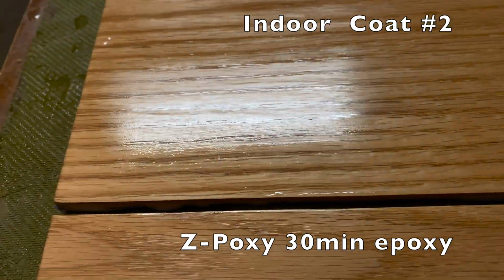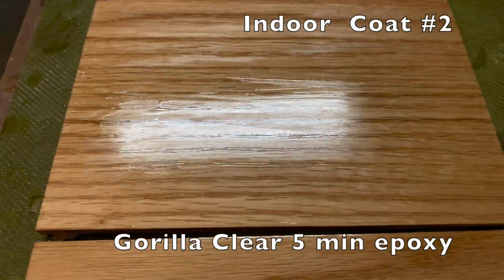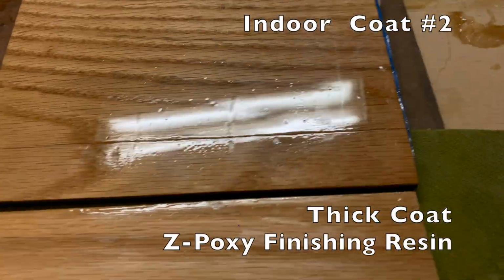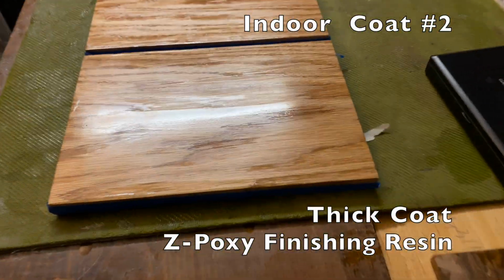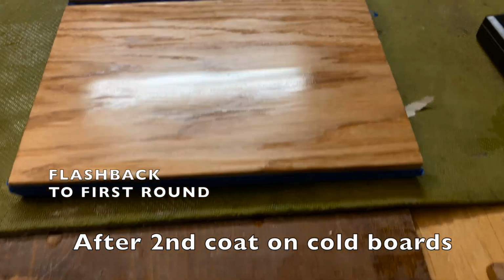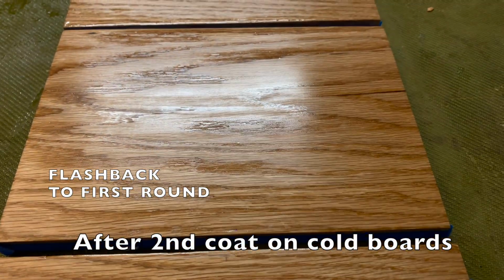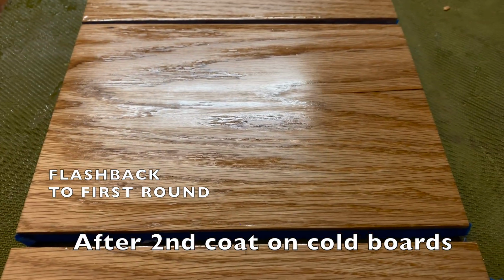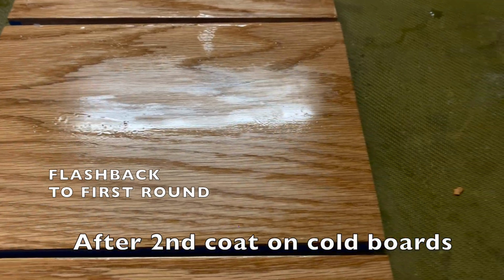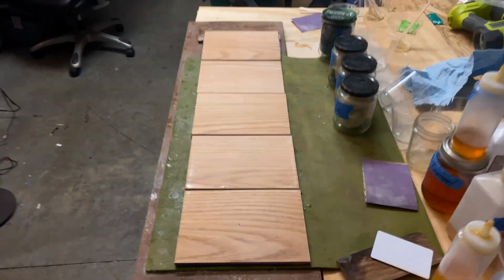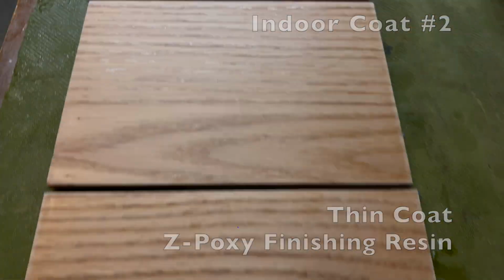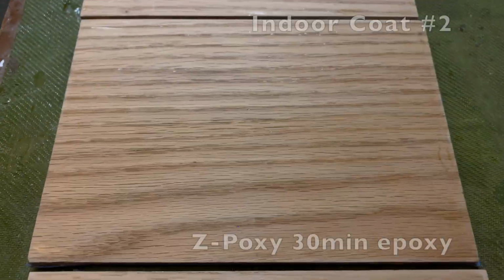After I finish showing these results, I'll show a clip of the boards we coated earlier during the first round in the cold. So here's the flashback to those boards that we coated during the first round in the garage. The second coat on these almost looked goopy and uneven in comparison. Once again, I sanded everything down to wood with 320 grit sandpaper in preparation for more finish.